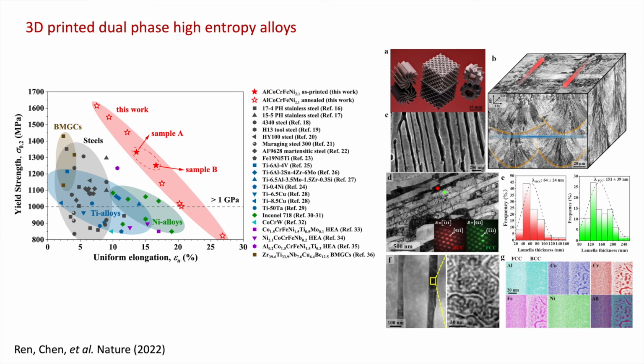A key microstructure feature in Ren's 3D printed high entropy alloy is the nano-lamellar microstructure. Due to the super fast cooling rate in 3D printing, the FCC and BCC plates, these alternating plates, don't have enough time to grow, and the average thickness is about a few hundred nanometers. The high-density FCC-BCC phase boundaries act as a new strengthening mechanism that contributes to the unprecedented strength and ductility.